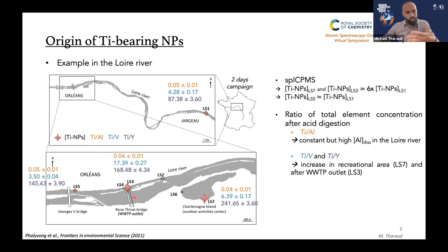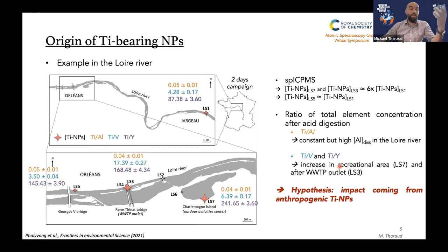So basically, when you have an anthropogenic input, we see that the concentration of Ti nanoparticles is increasing. And what we also see is that downstream of these two different areas, on the location number five, the concentration of nanoparticles is decreasing. So that's why we try to correlate this to a different elemental concentration ratio. And basically, when we focus on the titanium on vanadium and titanium on yttrium ratio, we are able to see that on the location where the concentration of nanoparticle is higher, the ratio of titanium on vanadium and titanium on yttrium is increasing. And as vanadium and yttrium are basically a tracer of geogenic background, we can make the hypothesis that there is an input of anthropogenic Ti nanoparticles and not natural Ti nanoparticles.